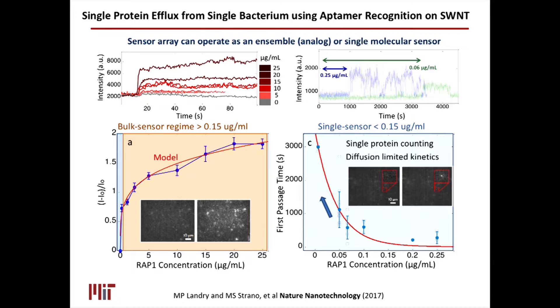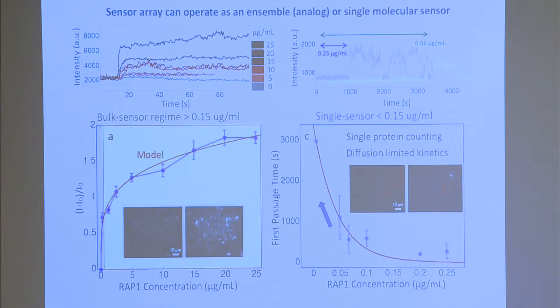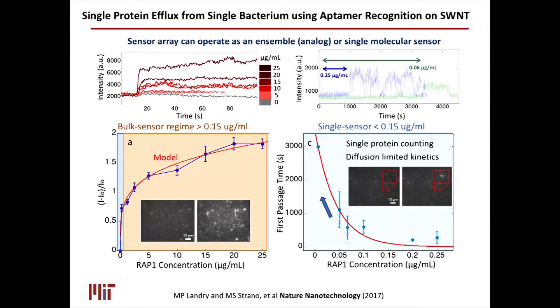She illustrates the advantage of a nanosensor that's so selective. If you take the sensor on a substrate and add up the signals from all sensor signals, you get an analog response curve. Just like any other sensor, there's a concentration below which you can't distinguish a signal from noise — a concentration detection limit in this mode. However, if you optically address just one nanosensor, you can count the stochastic fluctuations — every molecule that adsorbs and desorbs — and plot the first passage arrival time. This scales down to single molecule. You don't get anything for free: if there's a single molecule in this room and you're willing to wait long enough, you will detect it. This is a significant advance compared to where we were ten years ago — nanotechnology has given us the ultimate detection limit.